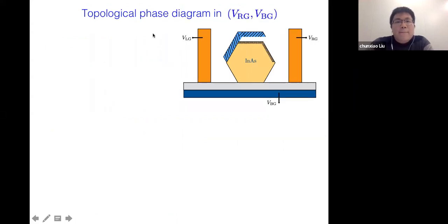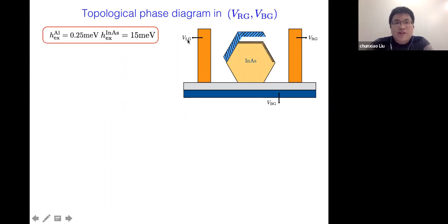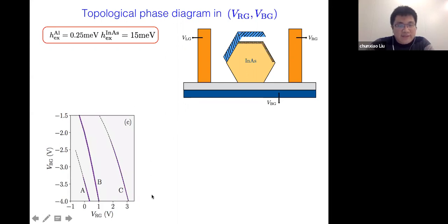Next, we study the topological phase diagram in terms of 2 gate voltages, the back gate voltage and the right gate voltage, while fixing the exchange coupling in both aluminum and indium arsenide. Here we didn't show the dependence on the left gate, because compared with the right gate, the left gate is less effective due to the screening effect from this metallic aluminum layer. Okay, so this is the calculated phase diagram as a function of the 2 gate voltages.